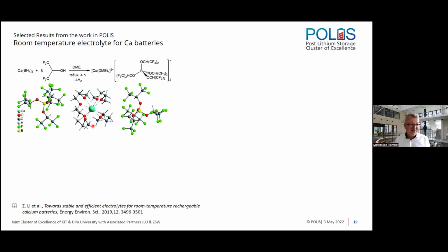And so what we did here is a very, very simple reaction. For a calcium electrolyte, you take calcium borohydride. This is something you can buy from Sigma Aldrich. And you let it react with fluorinated isopropanol. This is another commercial compound. So you let it drop inside, you have DME as a solvent, make a reflux. What you get is the product.